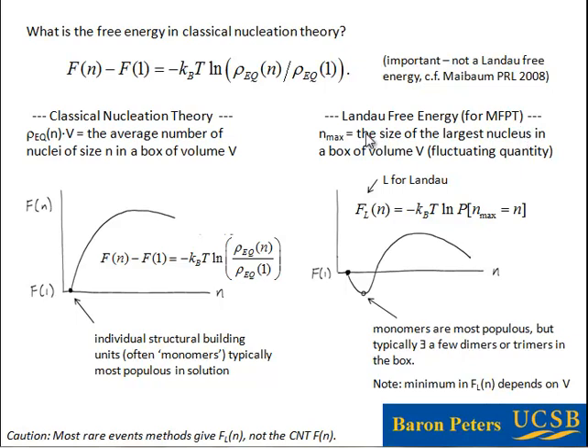At any given moment in time, if we could compute all nucleus sizes for all nuclei in the simulation box, we would have one nucleus that was the largest — call its size N_max, or just N. As a function of this N, we think about what is the probability that the largest nucleus has size N. We take the log, multiply by minus kT, and that gives the Landau free energy — the one obtainable by umbrella sampling.